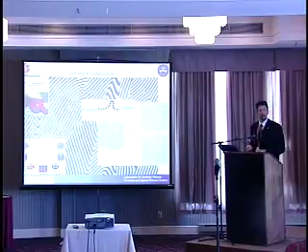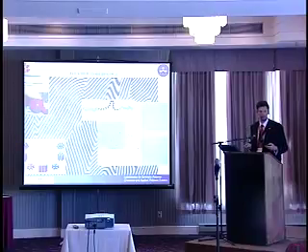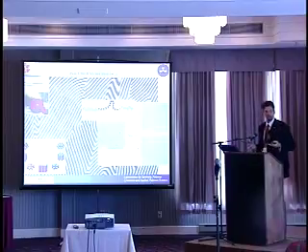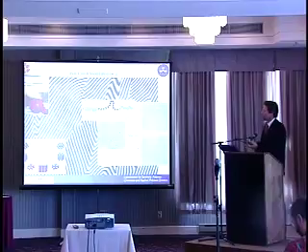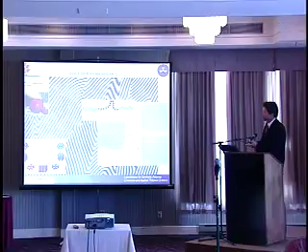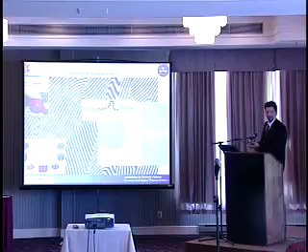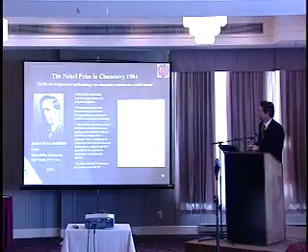Or if you want to think about using this directed assembly, which is done today, IBM just made a nice announcement, it was late last year, on building chips through lithography based not on photolithography definability, but on self-assembly of block copolymers. So where you actually have nanophase separation, nanophase lamellae, or spheres or columns, depending on where you want to hit this phase diagram. And then you can do specific reaction chemistry at some of those different phases and then get lithography. So you can start directing assembly to form structures using block copolymers.